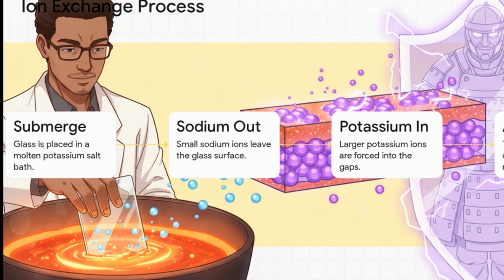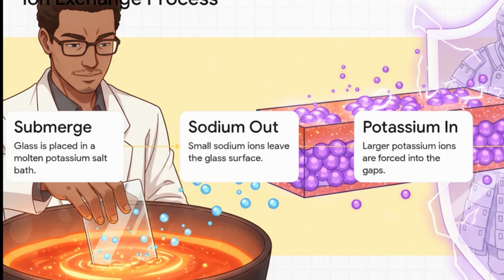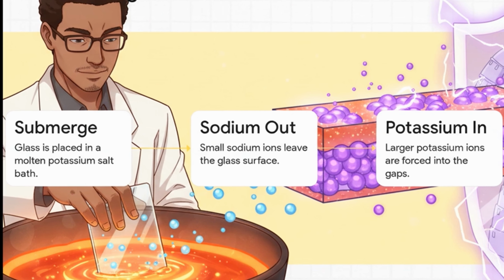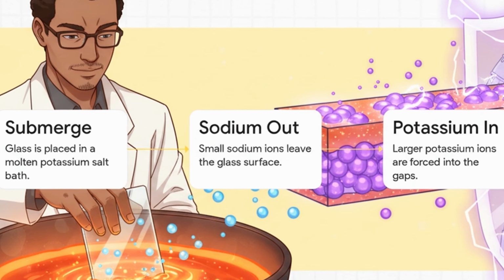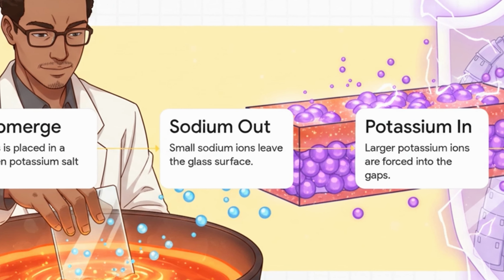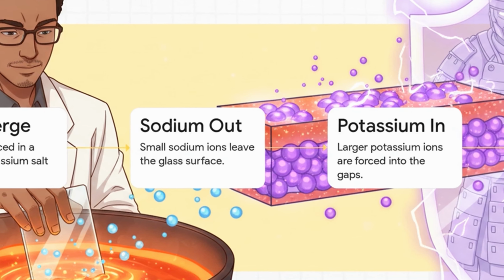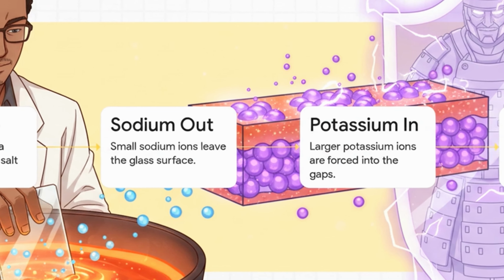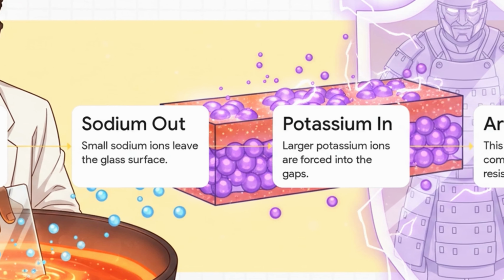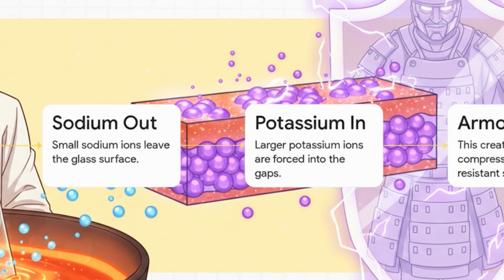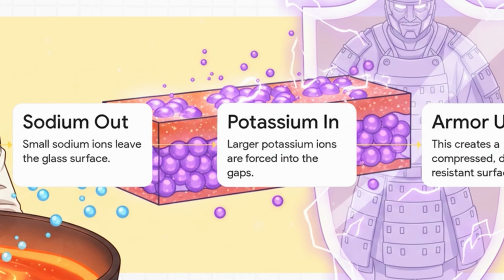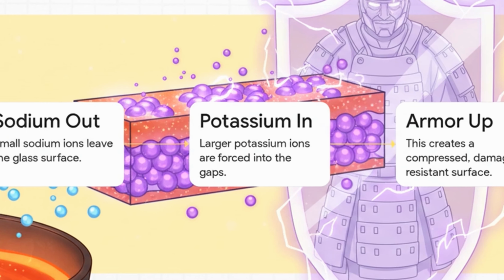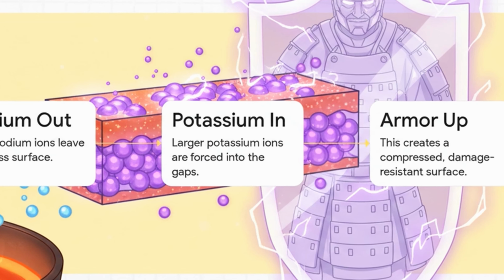Okay, so they take the sheet of glass and dip it into this crazy hot bath of molten potassium salt at about 400 degrees Celsius. The little sodium ions that are already in the glass flow out, and bigger potassium ions from the bath rush in to take their place. But since the potassium ions are bigger, they get crammed in there super tightly. This stuffing creates a layer of immense compression on the surface. It's like giving the glass an invisible suit of armor.